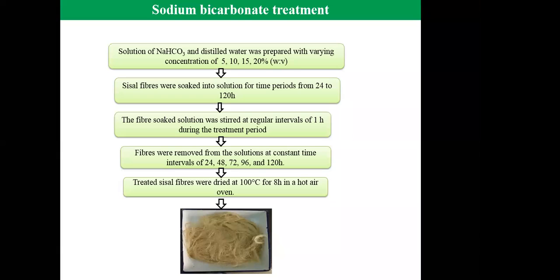Sisal fibers were soaked in the solution for a period of 24 to 120 hours. The solutions were stirred at regular intervals of 1 hour during the treatment period, and fibers were removed from the solution at constant intervals of time: 24, 48, 72, 96, and 120 hours. After that, these fibers were kept in a hot air oven at 100 degrees Celsius for 8 hours.